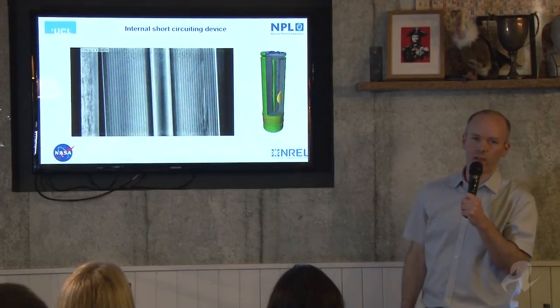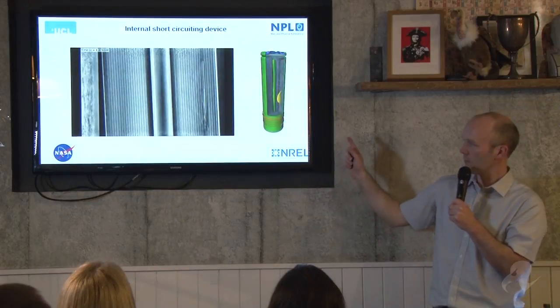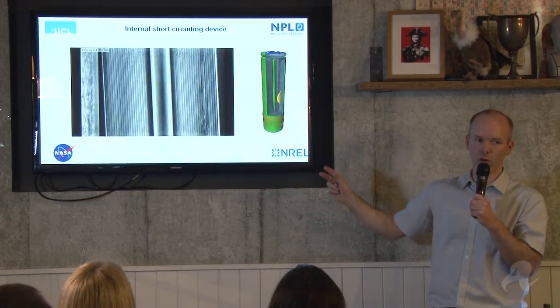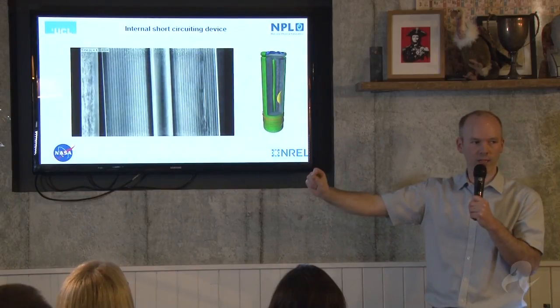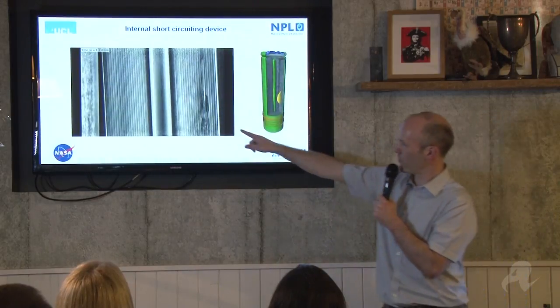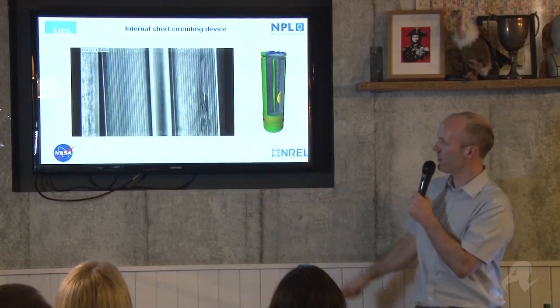This was really exciting because in the first video I showed you, we saw the effect of thermal runaway, but we didn't know where it started. Now we know where to shine our X-ray beam exactly in the cell, and so we've pinpointed it here. And you can see, for the first time, how the thermal runaway propagates. There had been a lot of argument about which direction it propagates in, and we can show from our work that it definitely propagates parallel to the current collectors, as you might expect. But it's very slow to propagate in the radial direction and also in the azimuthal direction, which is around the radius of the battery.